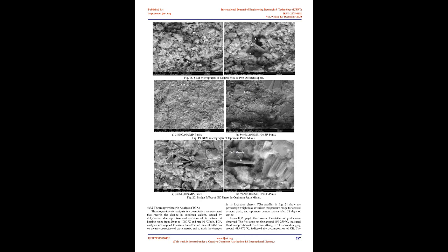This can be attributed to the filling effect of NC, MP, and SF, which led to significant decrease of voids ratio in the matrix. Furthermore, the pozzolanic feature of NC and SF enabled the reaction with the remaining calcium hydroxide that produced from cement hydration, forming more concentrations of CSH in the mixture. Table 11. The ultimate stress, peak strain, elastic modulus, resilience modulus, and toughness modulus of NSC and HSC samples.